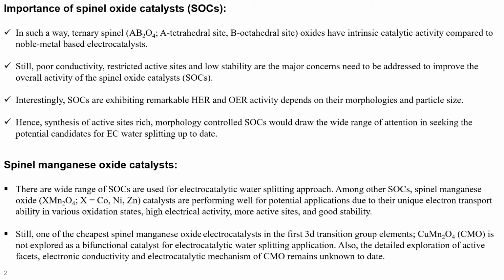Spinel manganese oxide catalyst. Among the other SOCs, specifically the spinel manganese oxide catalysts, that is XMn2O4, where X could be cobalt, nickel, zinc, copper, anything it may be. The spinel manganese oxide electrocatalysts perform well for potential applications due to their unique electron transport ability in various oxidation states, high electrical conductivity, more active sites, and good stability. Still, one of the cheapest spinel manganese oxide electrocatalysts in the first row 3D transition metal family, CuMn2O4, that is CMO, is not explored as a bifunctional catalyst for electrocatalytic water splitting application. Also, the detailed exploration of active facets, electronic conductivity and electrocatalytic mechanism of CMO still remains unknown.